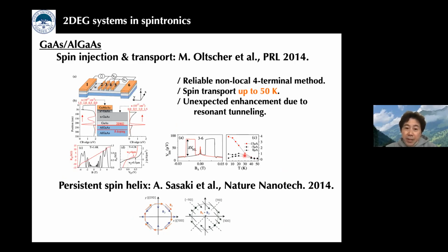Of course, gallium arsenide-based 2D is the other important material system for spintronics, and a group in Regensburg intensively studied these material systems. They reported successful spin transport up to 50 K, and also an unexpected enhancement of the spin signals due to the resonance tunneling effect. The other important achievement is the formation of the persistent spin helix state in these material systems, which was reported by a Japanese group. As shown here, we can control the Rashba and Dresselhaus type spin orbit interaction by changing the crystal directions and also bias voltages, and a persistent spin helix state where spins do not dissipate can be realized.